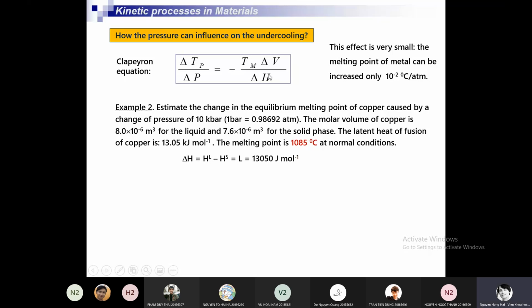So we have here Tm delta S is equal to the latent heat, and latent heat here is equal to 13,050 joule per mole. We convert kilojoule to joule. And then delta V here is the volume of liquid minus volume of solid. We have 8 minus 7.6, so we have 0.4 multiplied by 10 power minus 6 cubic meter. That is delta V.